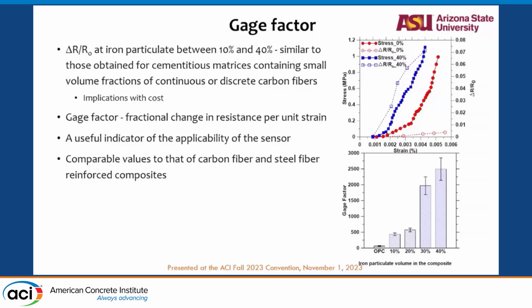based on the general flexural equation, we saw the strengths that were induced into the samples, and we plotted that against the delta R by R naught that we saw. For OPC, it's more or less flat, while for 40% it's quite significant.